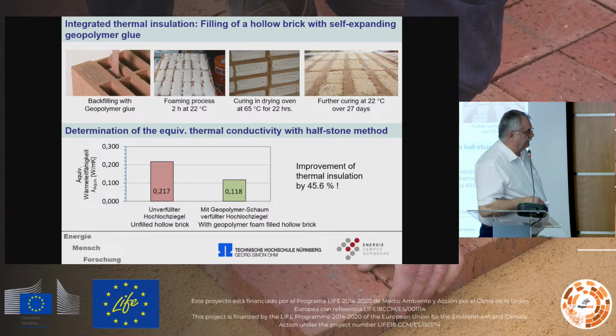Here you have the thermal insulation, the thermal conductivity from the hollow brick, 0.22 watt per meter Kelvin, and if you fill it and you make a new measurement, you see it is going down to 0.12 watt per meter Kelvin. So you can have an improvement of the thermal insulation of about 45.6%.